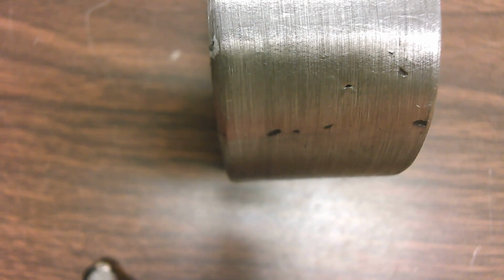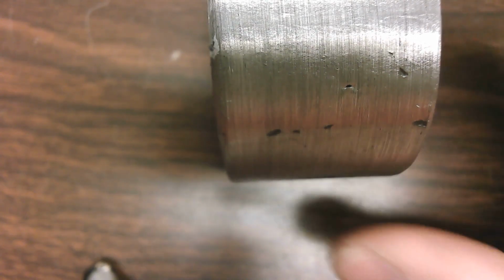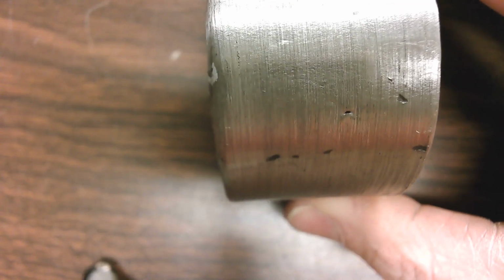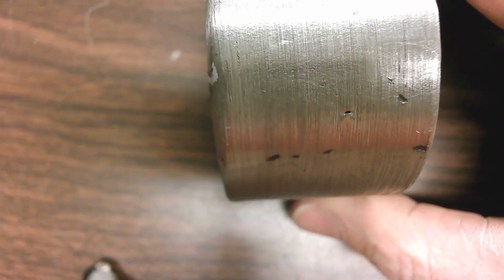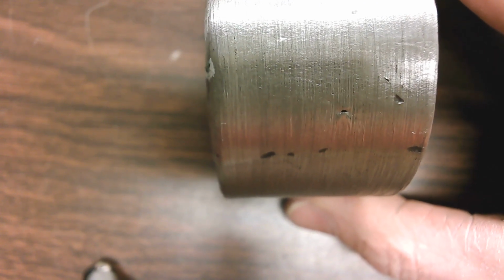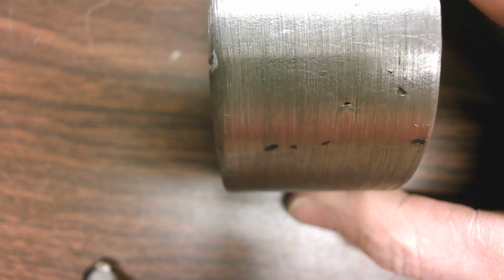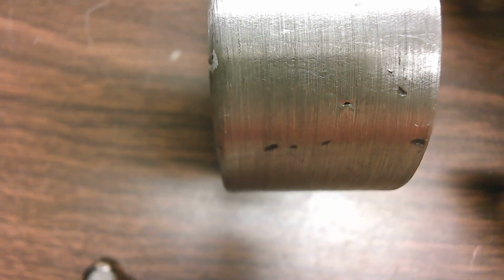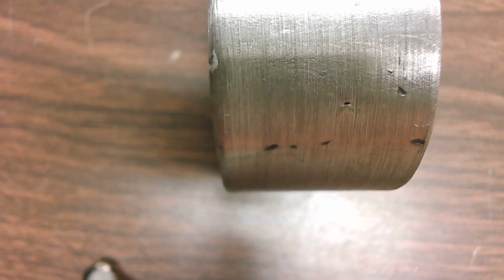The problem is, in order to pass a successful bend test, you need to pass both the face and the root. So the face passes, and for a grade, I grade them separately on their root versus their face. But in terms of actually passing the bend itself, if we're looking at the SENSE program, they have to pass both the face and the root on the same bend test. They can't pass a root on one and then weld up another one and just pass the face. They've got to pass both. So let's take a look at that root.